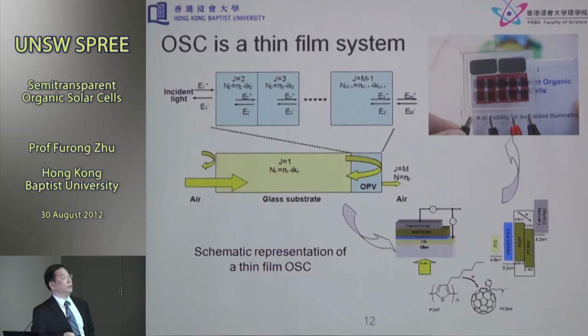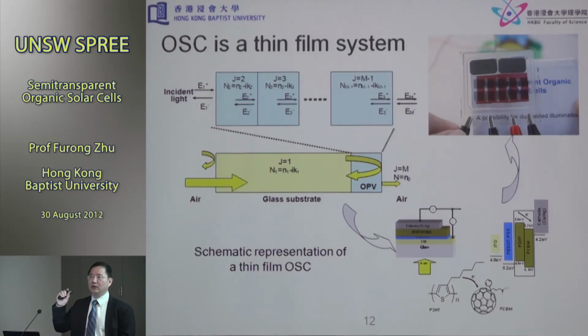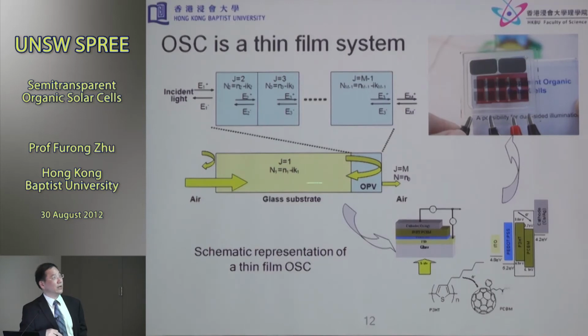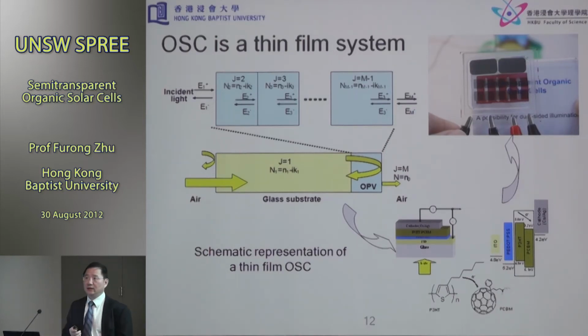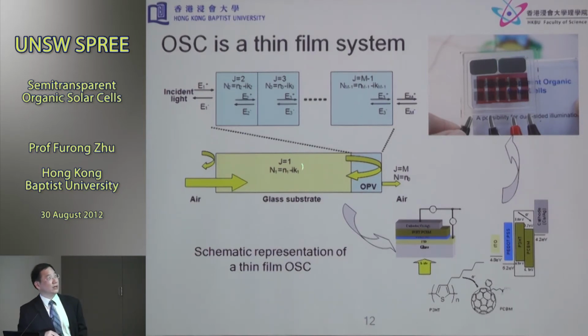So from an optical point of view, as I mentioned earlier, the active layer thickness that you need for organic solar cells is relatively thin. Assume that if you look at this cartoon, this is the glass substrate, typically 1 millimeter thick glass plate with ITO, then you have layers of organic materials. Finally, you have the cathode. So if you look at this stack, essentially it can be considered as a thin film system, right? So when light strikes the substrate, you have refractions. Some of the light will penetrate and get absorbed by the different layers, and eventually get reflected, bouncing back from the reflective cathode. Typically, silver or aluminum is used.